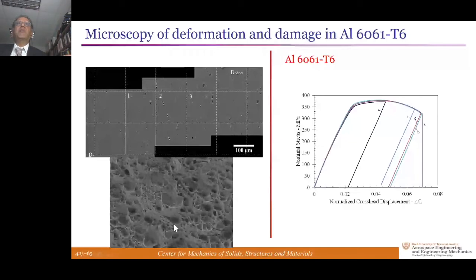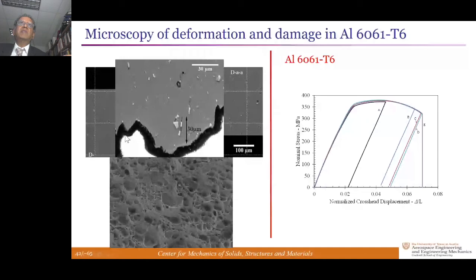They form at the very tail end of when the material is about to break, and furthermore, they're highly localized. If you make a section along this line and see just below the surface, how far below the surface do these dimples form? This is the surface of the fracture. These are sections below the surface. And if you go about 1 grain diameter or so, there's no more damage anywhere. So damage occurs late in the game. And I'll define what I mean by late in the game in a few minutes. And it occurs in a very localized manner. The rest is all plasticity.